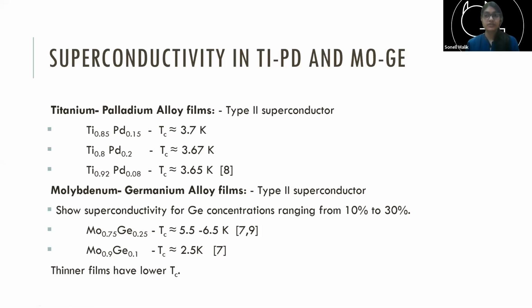You need to know your machine very well. You need to spend a lot of time. You need to make multiple samples to finally get the right concentration. And even when you get that right, sometimes things don't work out, or in the next one there might be a little bit more oxygen than you would want, and that could deteriorate your transition temperature. So essentially, experiments are hard.